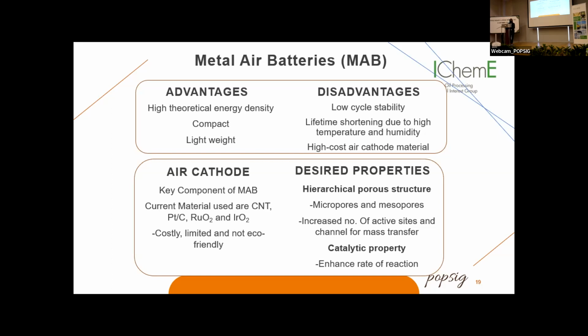So the air cathode is the key component of metal air battery. The current materials used are carbon nanotubes, platinum on carbon, ruthenium oxide, and iridium oxide. These materials are costly, limited, and not eco-friendly. So for an air cathode to perform well, it should have hierarchical pore structure, which is a mixture of micropores and mesopores, as it increases the number of active sites and channeling for mass transfer. Secondly, it should also have good catalytic properties to enhance the rate of reaction.